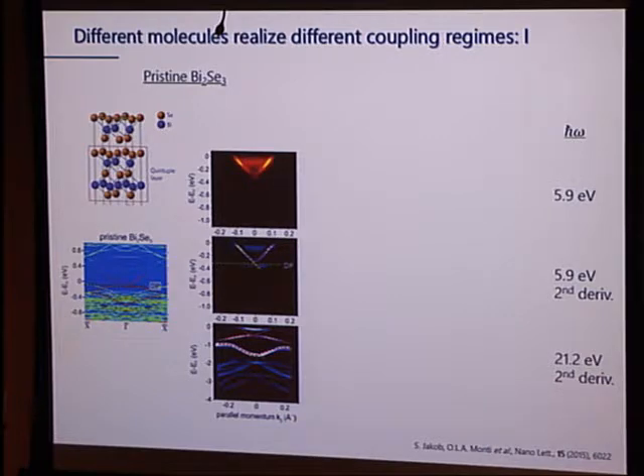In each case, we're going to measure the band structure, the electronic structure of the material, with different scenarios of molecules adsorbed on the surface. So to begin with, let's just look at what the bismuth selenide band structure looks like. And like I told you, here's the Dirac cone. These are the surface states. This is the onset, just barely, of the conduction band here. If we look a little bit deeper, you see the various valence band levels and deeper that show up. Okay, so this is just a regular band structure.